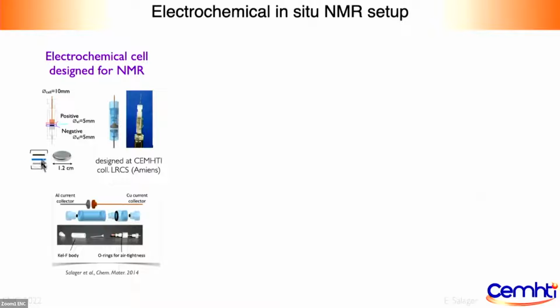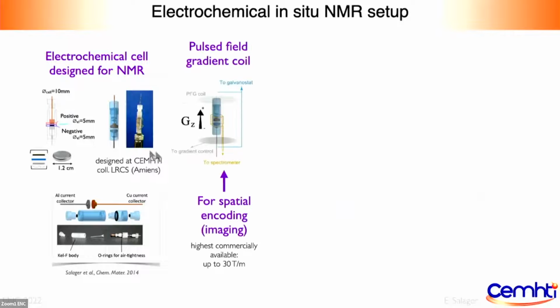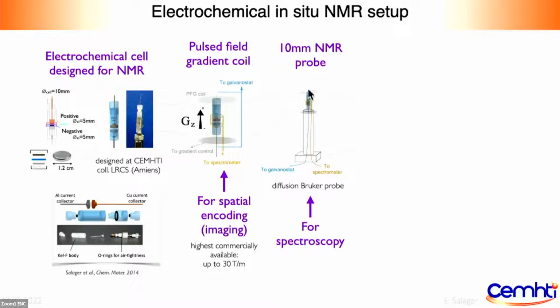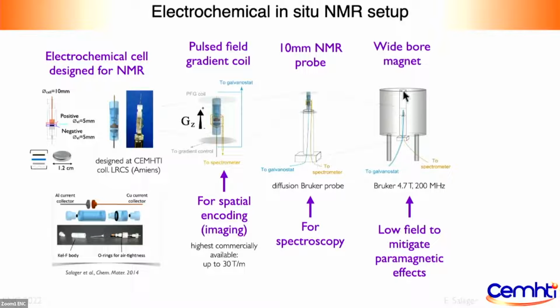It's the same principle as a coin cell, except that we're inside a plastic casing, and we have a sandwich of the positive electrode and the negative electrode. We designed this back in 2014 when there were not so many people doing in situ NMR. We designed it so that it could fit inside a saddle coil of a diffusion probe from Bruker, so that we would have a strong pulse field gradient along the Z direction, and that we could localize the spectra. This fits inside a diffusion probe, and then you bring it into the magnet. The battery is located here at the center of the RF coil. You connect it to a galvanostat for charge and discharge, and at the same time, you record the NMR spectrum.